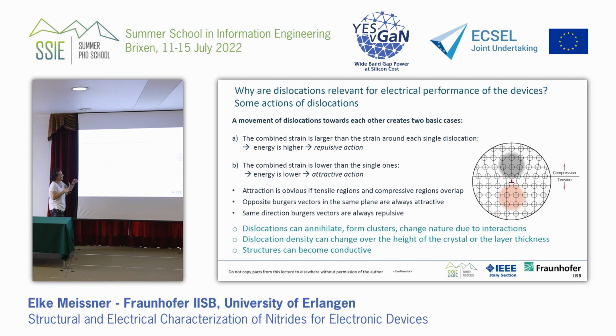And this strain region is something that is active, even though the displacement of the atoms in the core of the dislocation doesn't count. You have to keep in mind that there is a strain field around, and this strained material is also doing something. This stores the energy.